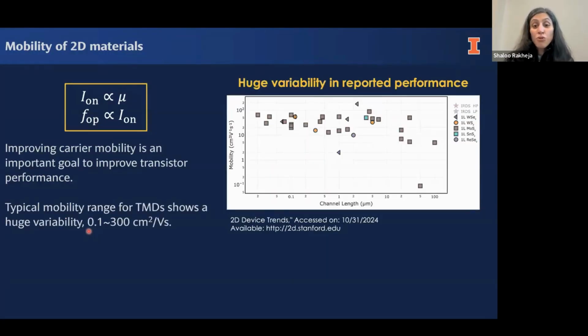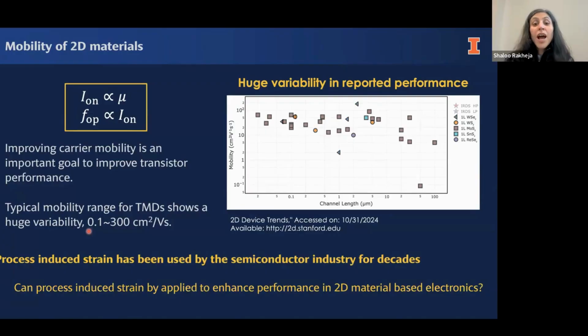If you look at 2D materials mobility, it's all over the map. You can find papers that report mobility in the range of 0.1 to 300 centimeters squared per volt second at room temperature. So this is a huge variability. From an experimental standpoint, we need to be able to develop processes where this parameter is tightly controlled. And on the theoretical front, we need to be able to understand how we can control this parameter, but also optimize this parameter for getting the performance that we desire from these 2D material-based electronics.